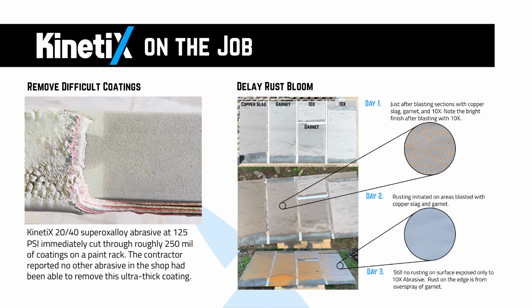And it turns out that rusting of bare metal is an inherently slow process. It can only happen quickly if there are iron or water-soluble salt residues left behind with embedded particles to initiate and accelerate the corrosion reactions. Rust bloom is delayed with 10X abrasives because they leave a clean, bare steel finish. Our shipyard customers are noticing. Just recently we had a section of a ship that was blasted to an SP6 finish and then had to sit before being recoated, and after 3 weeks it was still SP6.